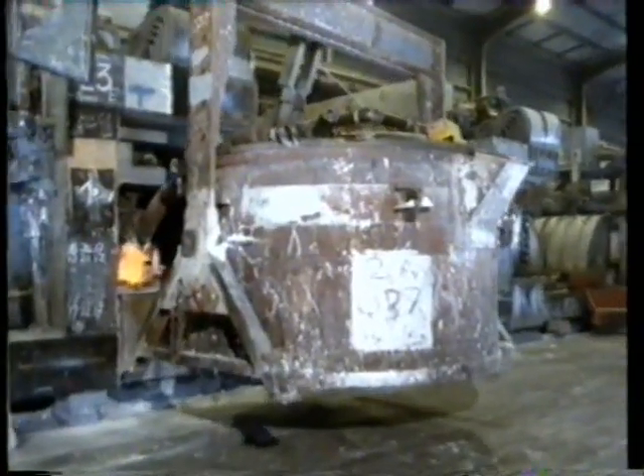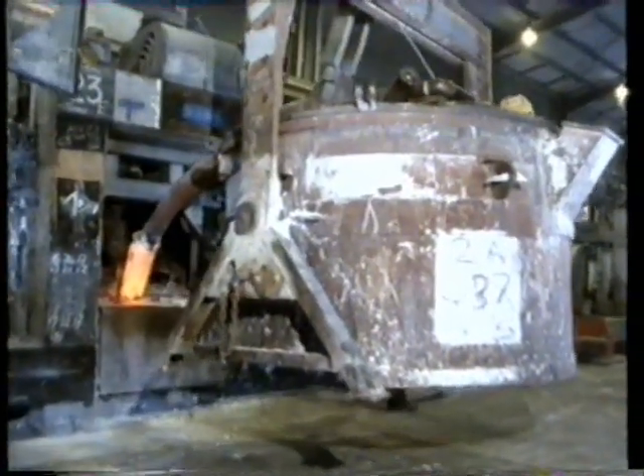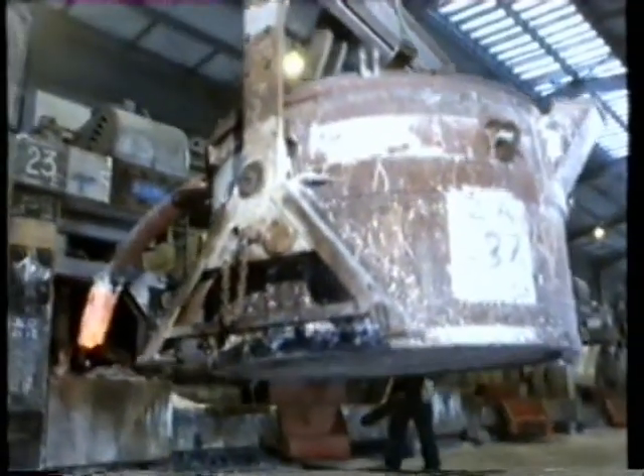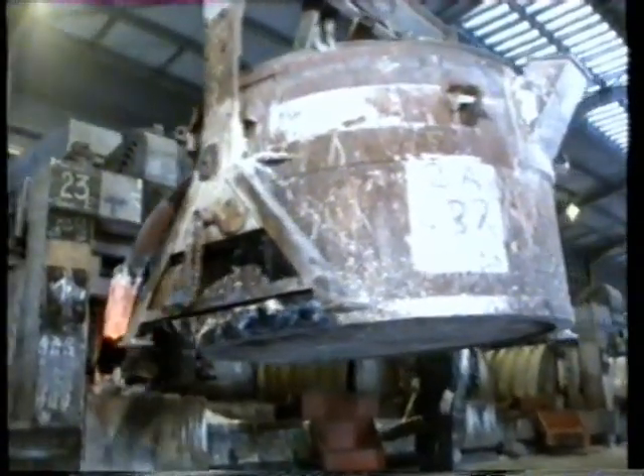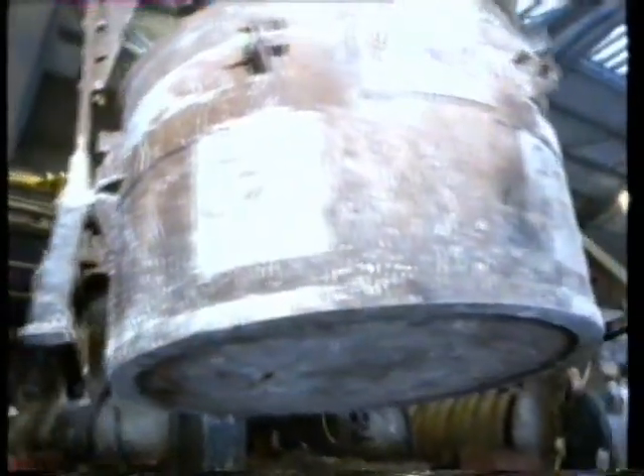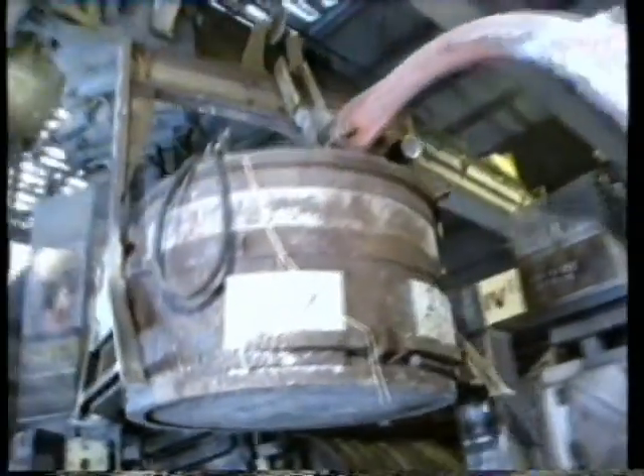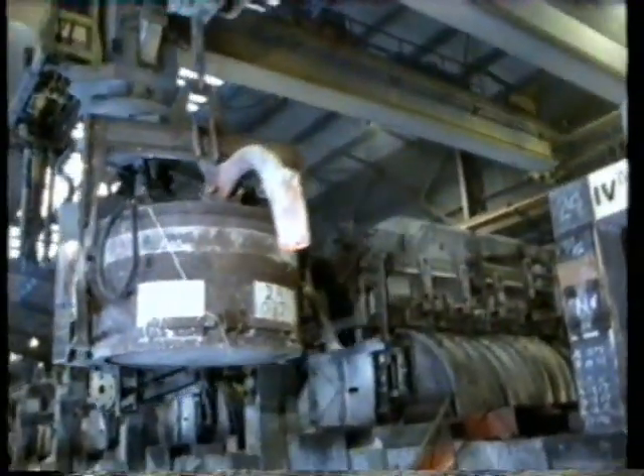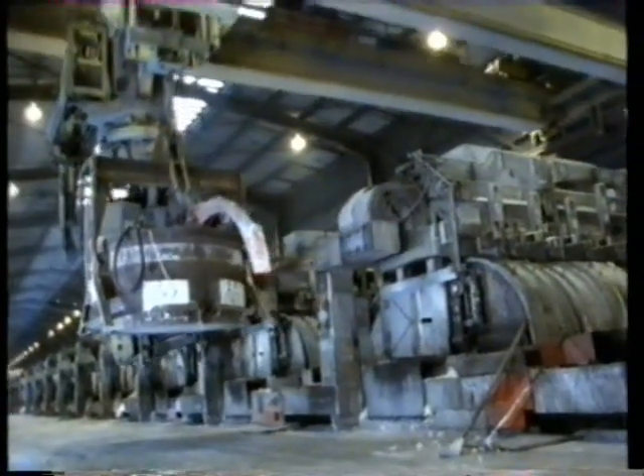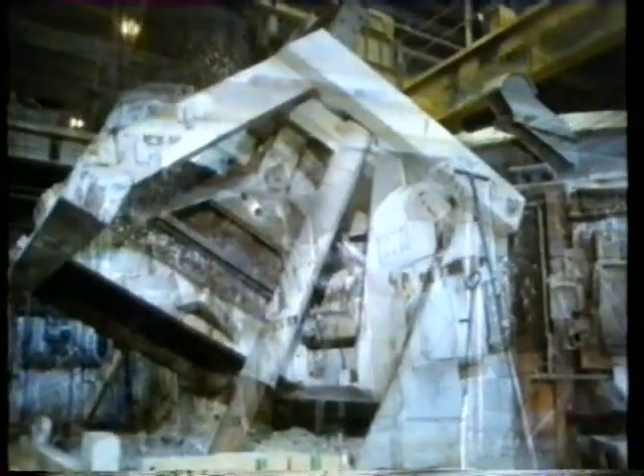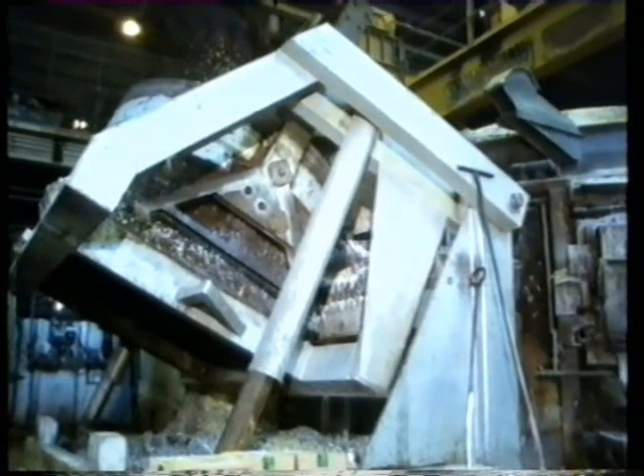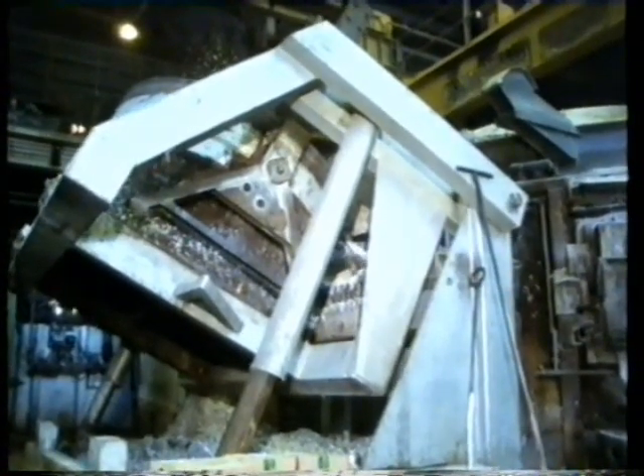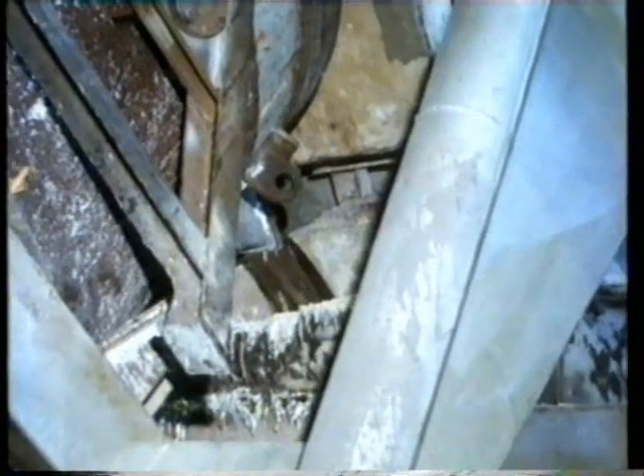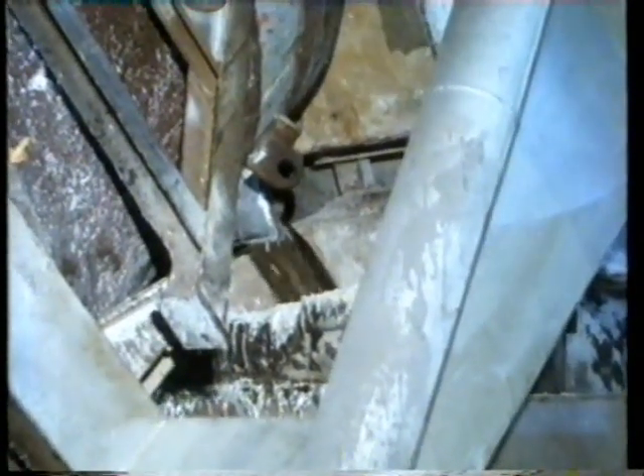Approximately 1 ton of aluminium is produced in each cell per day. This is drawn off by a vacuum tube into a crucible. This holds about 5 tons of liquid aluminium at over 900 degrees C. It's poured into holding furnaces where it's kept molten. Other elements can be added to produce aluminium alloys for various uses, such as iron, silicon, manganese, magnesium.